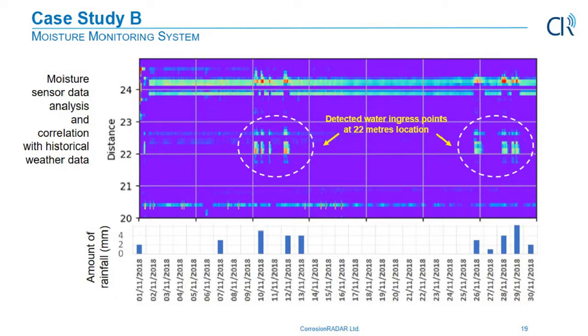And you see at around the 22 meters location, we started to see some patterns of rainfall, and it was highly correlated with the rainfall in that region. So water is getting in. Normally it is not supposed to, and that's the precise reason why CUI happens. But there's more information here. One is the location of that problem, so customers can actually prioritize the inspection at that location and deprioritize inspection at other locations. And then also the wetting and drying cycles, which are actually one notch higher of corrosion severity, because these coatings do not like these drying and wetting cycles, and this is happening here. So this will be a high risk area.